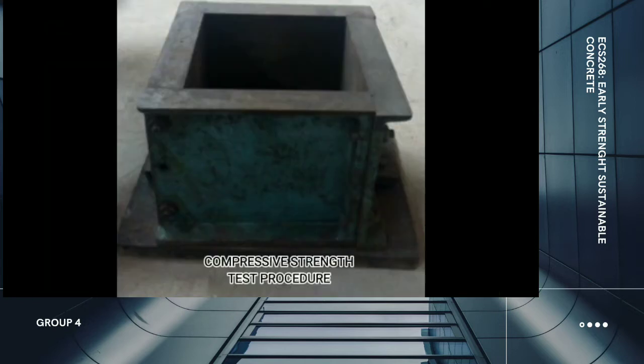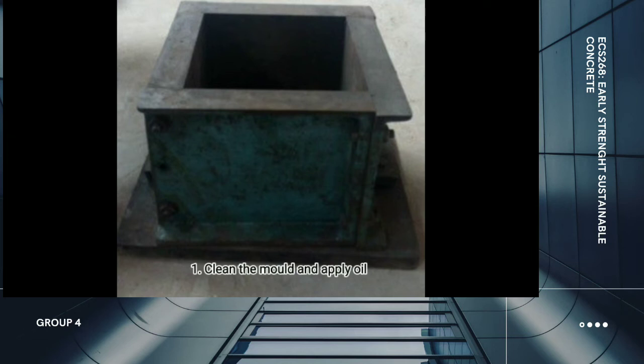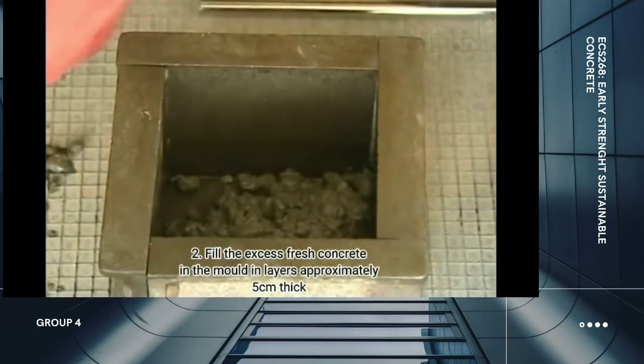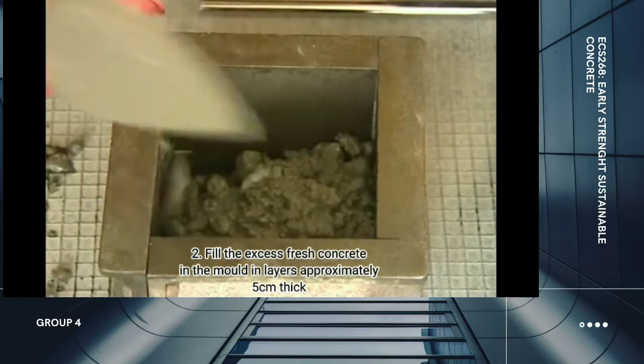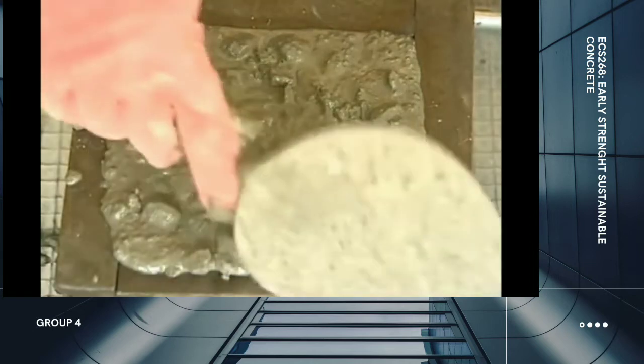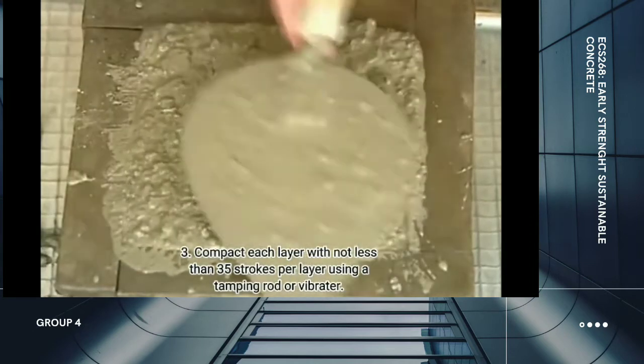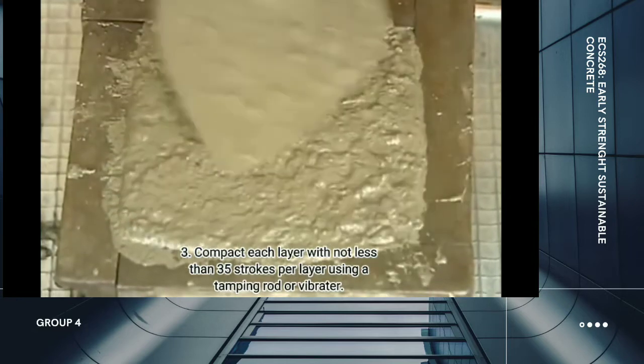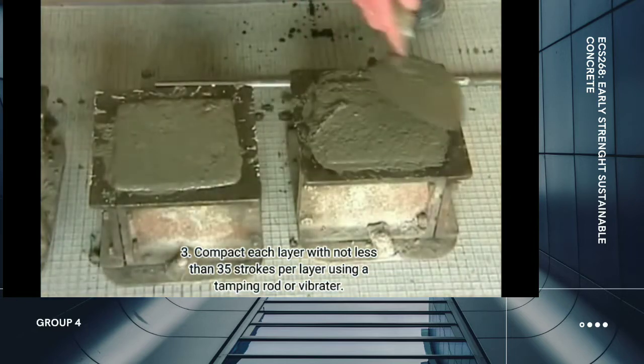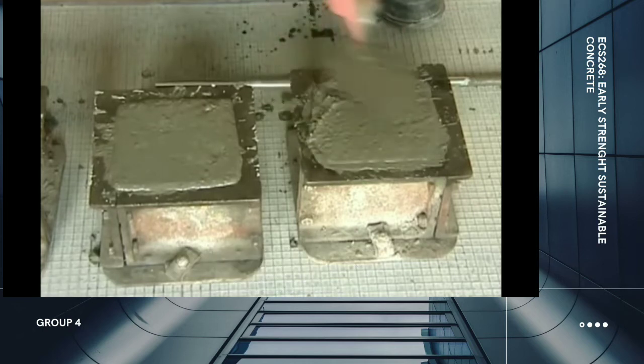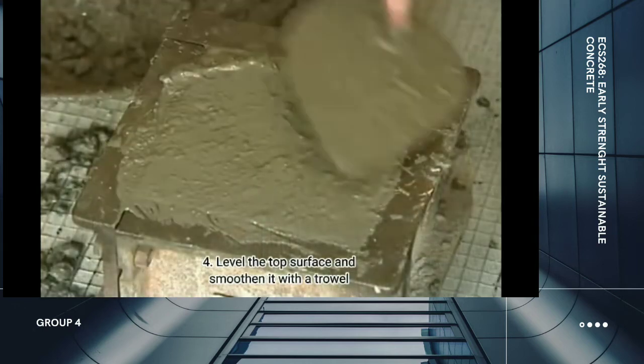For the compressive strength test procedure, first we need to clean the mold and apply oil. Fill the fresh concrete into the mold in layers approximately 5 cm thick. Compact each layer with not less than 35 strokes per layer using a tamping rod, or you can also use a vibrator. Level the top surface and smoothen it with a trowel.